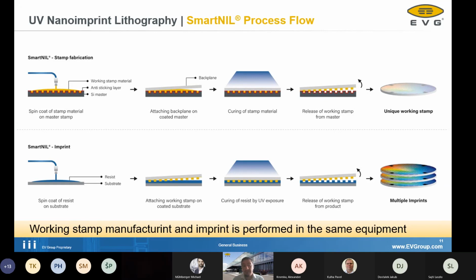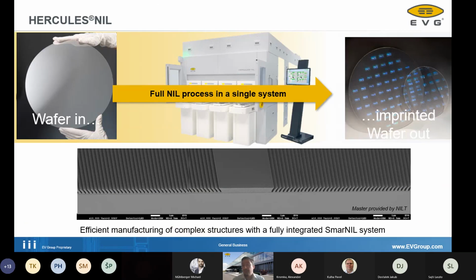So you put the imprint resin, and it's a functional resin that you need here, which also has to have the right optical properties. In case of augmented reality waveguides, it's a very high refractive index. Nowadays, the resin suppliers are capable to deliver materials with refractive index up to 1.9. But still, it has to have very good filling properties. And of course, the interaction of surface energies and so on of the stamp and the resin is very important. And of course, again, the process has to be very efficient, that you have fast curing materials, high yielding release, and then you can make multiple imprints from one working stamp and do this all in the same equipment. These are things we have mastered together with Wave Optics, but not only with them alone.